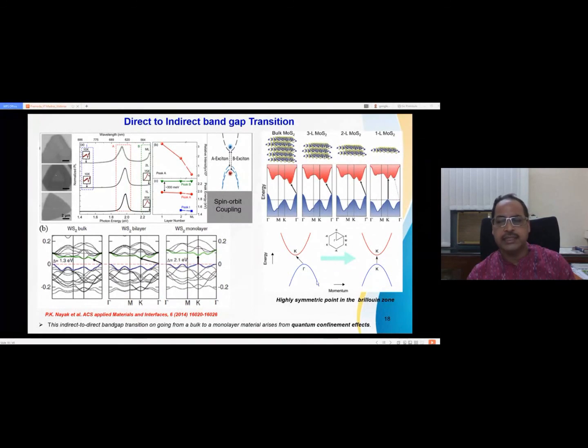As it is a hexagonal lattice, this is the first Brillouin zone of the hexagonal lattice. These are the high symmetry points. So you can calculate the electronic band structure along these high symmetry points. Here I have shown this experimental graph. You can see for a single layer, bilayer, and multilayer WS2 that there is a change in the band gap, from 2, then 1.9, and so on. So this is the direct band gap to indirect band gap transition.